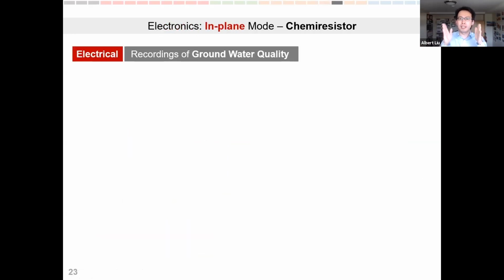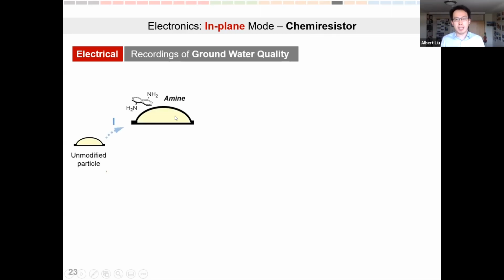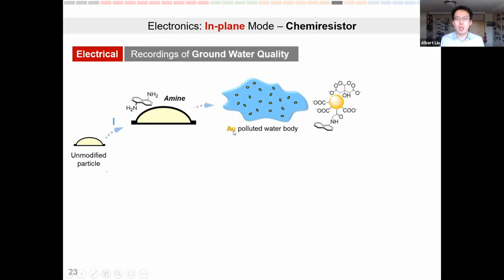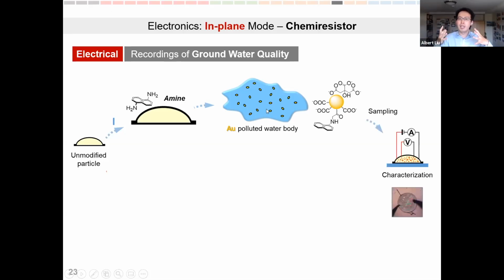So I want to introduce how we can then build chemical sensing and information recording into this kind of electronic colloidal particle that we have just built. In terms of chemical sensing, we leverage something called a chemical resistor that is built within the two-dimensional material themselves, which changes its conductivity based on the chemical analyte it detects. So we're making these microscopic dumplings that have the two-dimensional material skin, in this case graphene, and the polymeric interior. By grafting amine functionality onto the graphene, we're able to use the amine functionality to grab onto gold nanoparticles that are distributed into a groundwater source. So by harvesting our microparticles back and basically querying its surface conductivity, we can measure whether or not our particle has seen gold nanoparticles in groundwater.